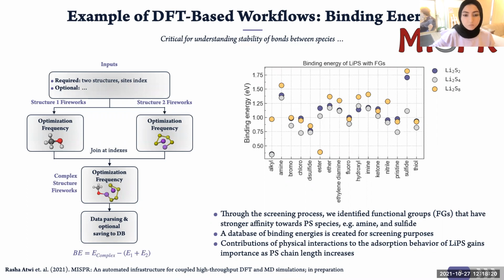We use this workflow in the lithium-sulfur project to identify possible functional groups that we can attach on the cathode surface, a carbon cathode surface in the lithium-sulfur battery, and to identify mainly functional groups that have high binding affinity towards the polysulfide species that exist in the bulk solution. This represents a way of trapping the polysulfide on the surface and preventing their diffusion to the electrolyte. For example, we found that amine and sulfide groups represent promising functional group candidates that can be used in further or more detailed simulations and experimental studies.